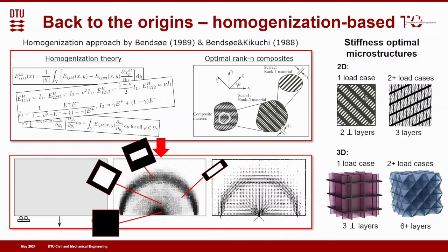If we have two or more load cases, we also know the optimal microstructures. They can be found analytically. In 3D, interestingly, for one load case, the optimal microstructure is sort of a square or rectangular hole structure, and it's a closed wall cell. And if you have two or more load cases, there are more layers in different directions, up to 6 or 7, actually, if you want symmetries and periodicity. But this is an interesting point to make.